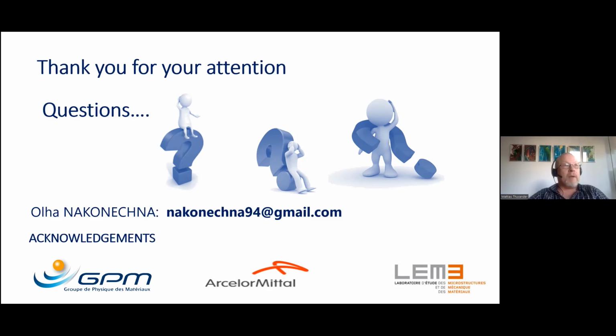Thank you. I mean, could you think of any reason that the manganese difference from atom probe could be wrong? Not really, because it has quite a close evaporation rate to iron, which is the matrix. Of course, there could be a question about the interface, because there can be some aberrations, some local magnification effect. But there is also the segregation of carbon and segregation of manganese, so we expect that it will compensate a bit. So we expect that the observed data represent the situation very well.